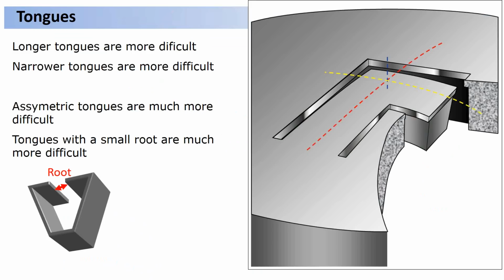What we're trying to do here is show you some things where small changes in the design can make the die much more extrudable. A much more extrudable die means more pounds per hour, which means to get your pounds, you've rented less press time, which means your costs go down. So this isn't just looking at that from an extruder's viewpoint, this is also looking at it from an extrusion customer viewpoint. Small changes in your section, and we're going to show you two in a few minutes, can actually increase the functionality that you want whilst making it easier to push. You can get a better product at a higher productivity with some of the tricks we want to show you.